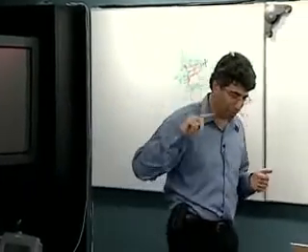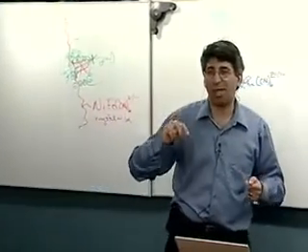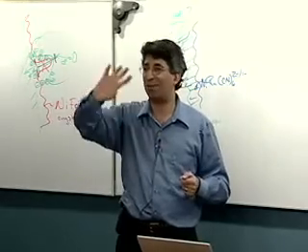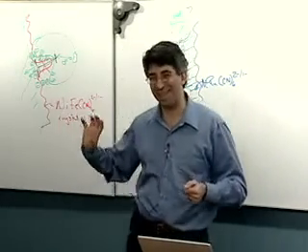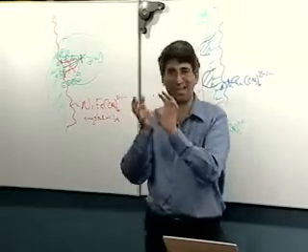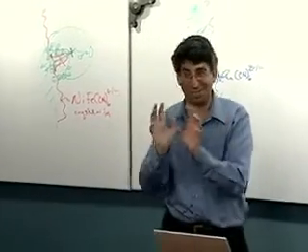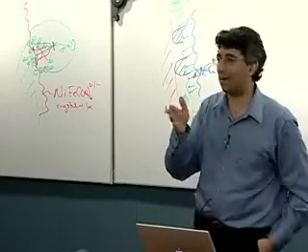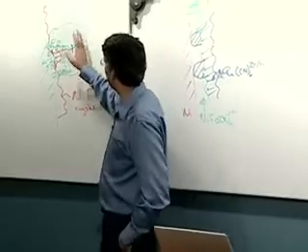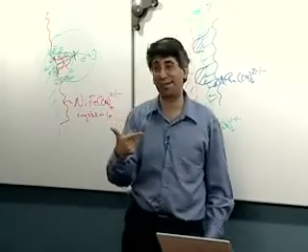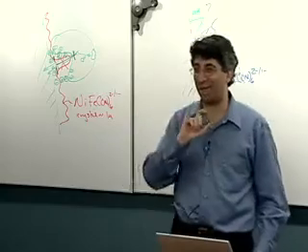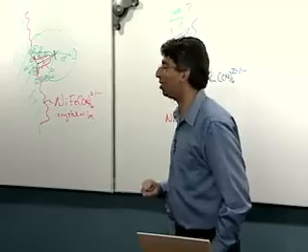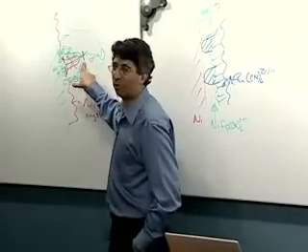The first group was not really biochemically capable, and so some of their enzyme was falling apart. And when it fell apart, the flavins came out, and there was your soluble mediator. And the second group came along, and they made sure their enzymes were pristine and intact with no soluble component, and they couldn't make it work. So anytime you're doing the electrochemistry or the redox titration, you have the possibility of some of the flavin coming out, and then its redox potential changes, and you see things that are not real. So there certainly has to be some skepticism in the reported redox potentials.